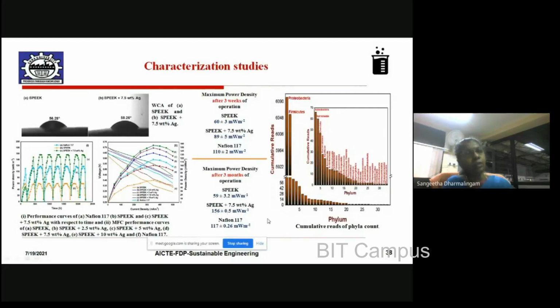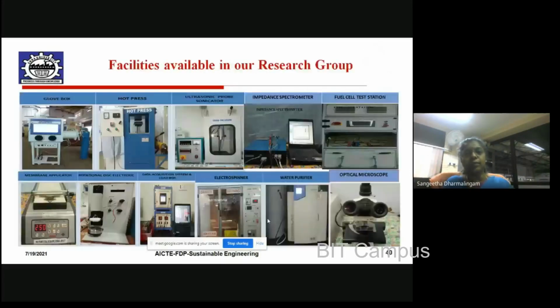But at the same time, we should remember the silver will also go and kill the microorganisms that may be present otherwise in the anodic chamber. You have to make sure that the silver is not leached out of the membrane. At the same time, it is present in the membrane to avoid more of these organisms getting attached to the surface of the membrane, so that over a long period of time it is able to perform. So we were able to get some good promising results, and all these have been published.